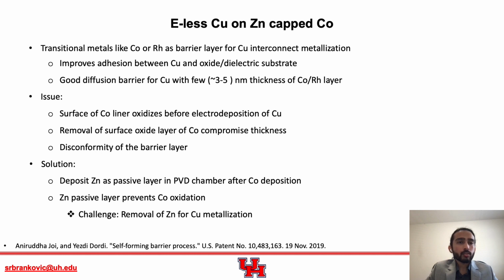However, there are several issues with this approach. First problem is that once cobalt is deposited in the PVD chamber and once it is taken out, the surface would oxidize before electrodeposition of copper. So the removal of the surface oxide of the cobalt is not so trivial. And since we have very little thickness, about 3 to 5 nanometer, any removal of this oxide layer could compromise the thickness and it could lead to nonconformity of the barrier layer.